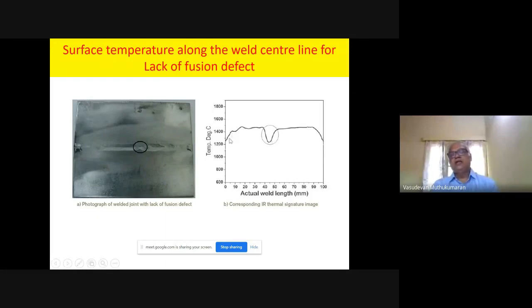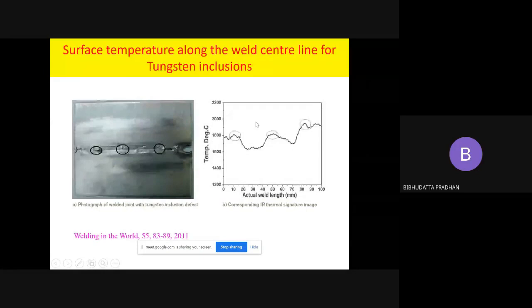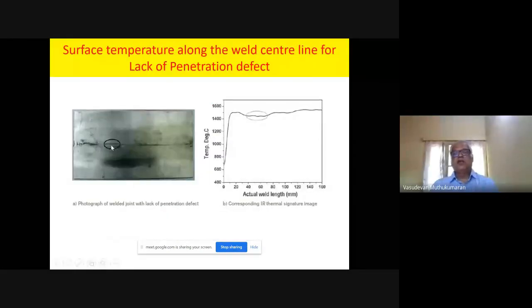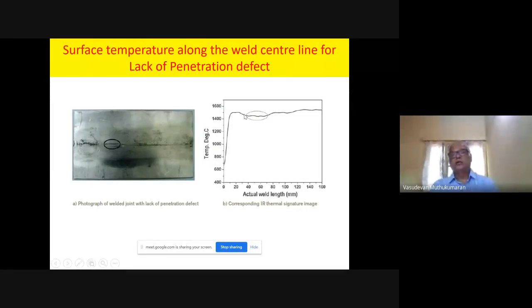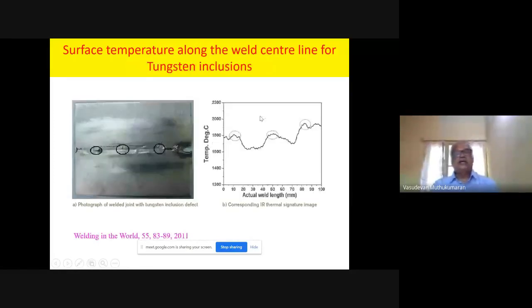You can see that there is a dip in your temperature curve. This is typical of lack of fusion defects we could capture using the IR camera, and this is lack of penetration. You can see here again the lack of penetration defect, which could manifest as you can see, the dip in the temperature curve. Again, these are tungsten inclusions we introduced in the weld joint that also showed some deviation from the normal surface temperature distribution. We could use this as a signature of various defects for detecting during actual welding. So these are the strategies we would like to adopt during intelligent welding.